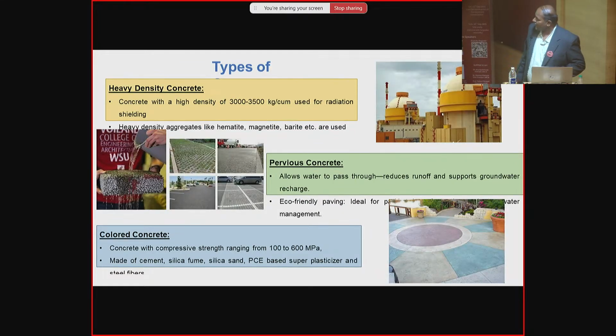And the heavy density concrete, I am just giving the different types of concrete so that you can understand, for the architectural students. So concrete generally has a density of around 2,400 kg per meter cube. By changing the aggregate type, like hematite aggregate or barite aggregate, we can make a concrete with a high density, typically around 3,400 kg per meter cube. And this type of concrete is used in nuclear containment structures, those kinds of places, where radiation is a criterion. And we have pervious concrete.